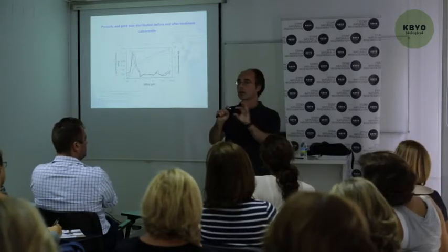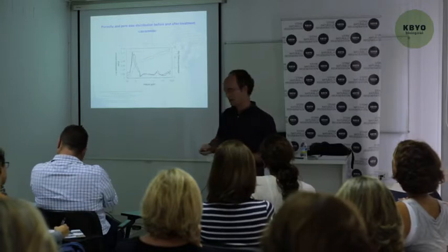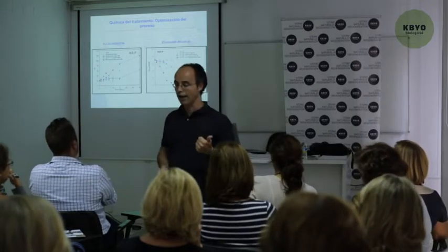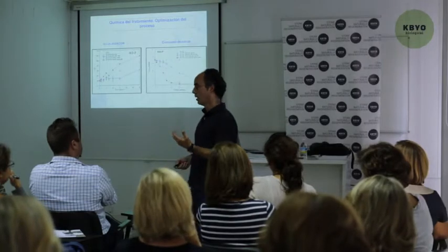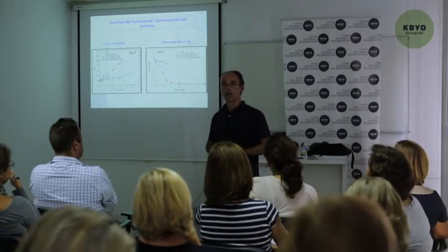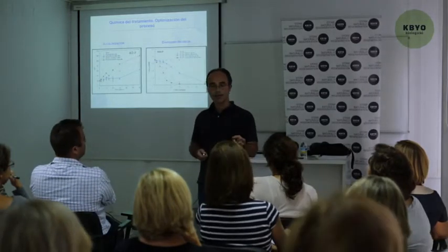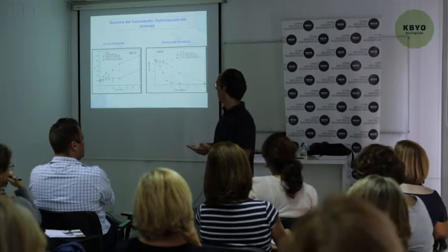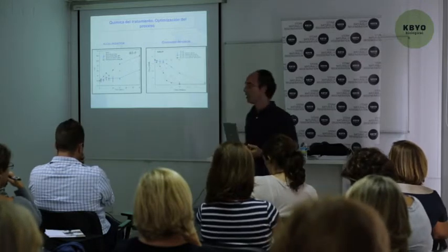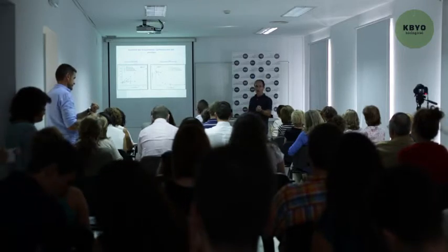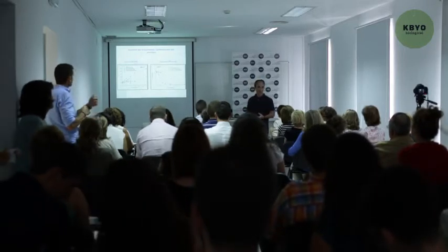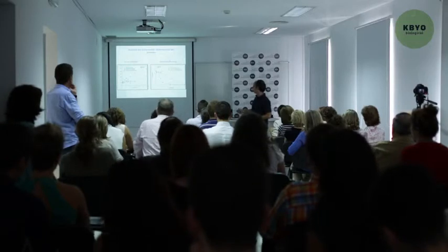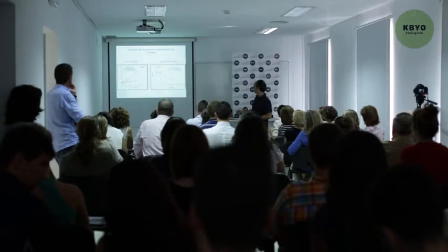To optimize the treatment, we did geochemical controls to check the evolution of the culture mediums once the nourishing solution has been applied. Observing the evolution of pH, we see that when bacteria develop their metabolism, they increase the pH. pH can increase to highly alkaline. Regarding the calcium consumption, the calcium withdraws from the medium because it precipitates as calcium carbonate.